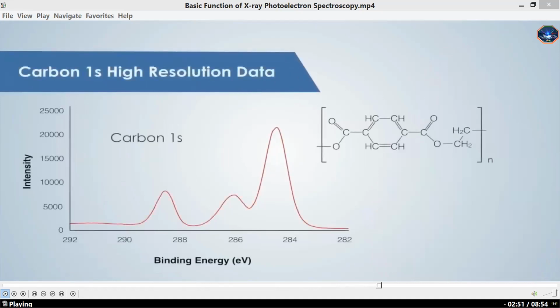Now let's return to the carbon 1s spectrum of PET to assign the peaks. The component at the lowest binding energy is due to the carbon atoms bound to other carbon atoms, labeled A. The peak at 286 eV corresponds to the carbon atoms bound to one oxygen atom, marked B. And the peak just above 288 eV corresponds to the carbon atoms bound to 2 oxygen atoms, marked C.